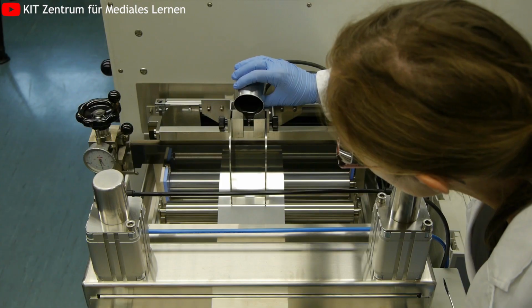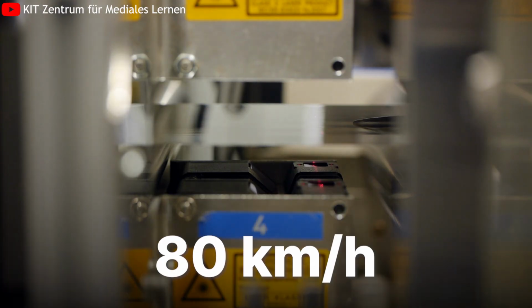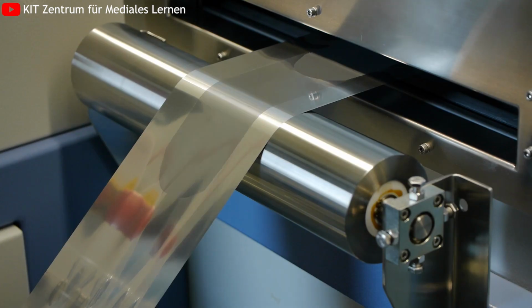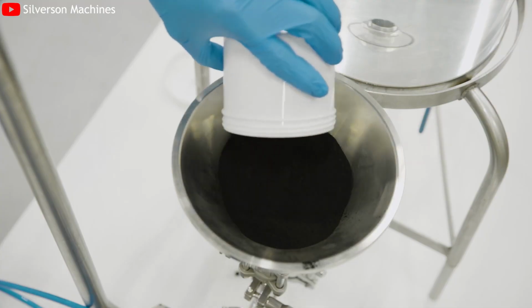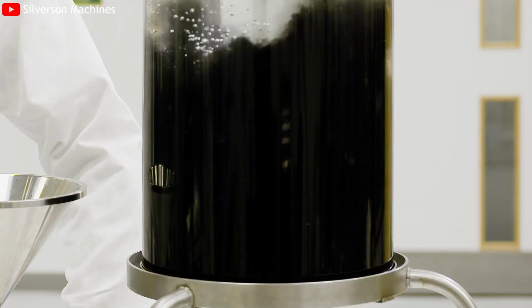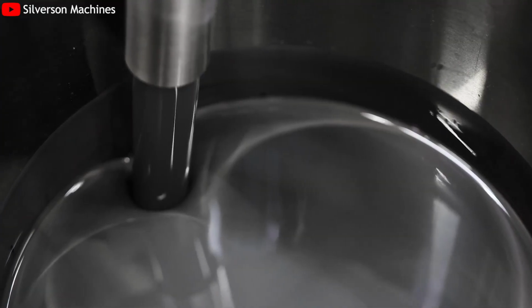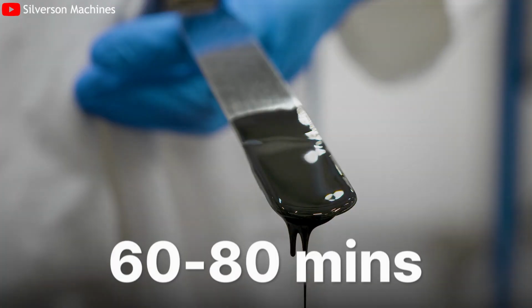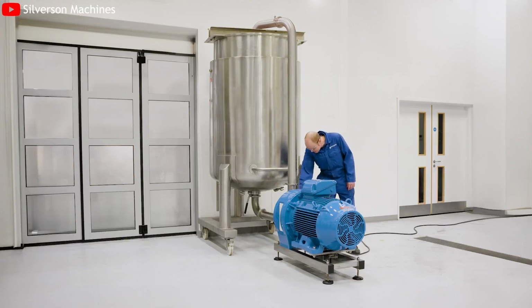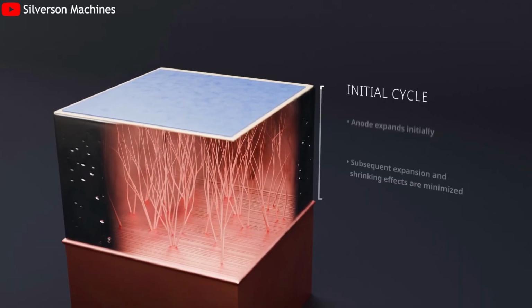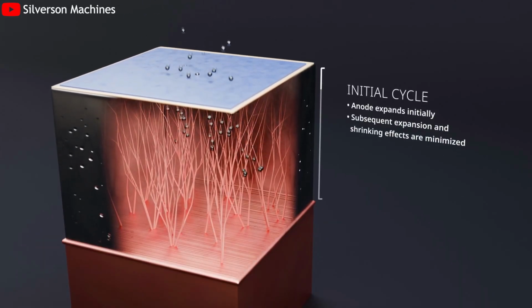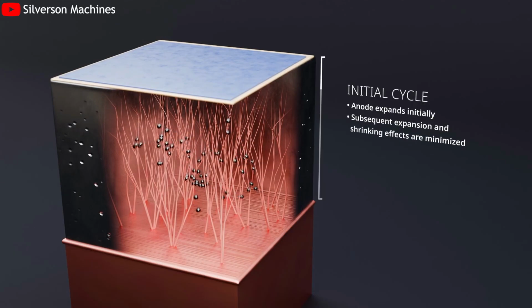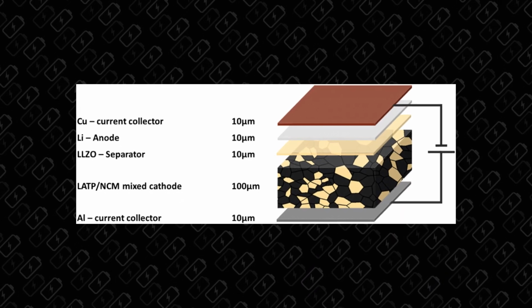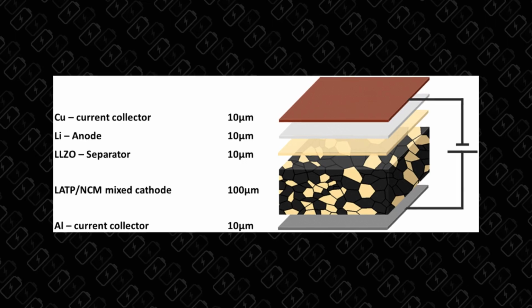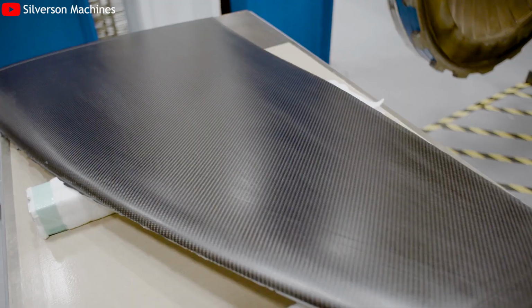Imagine trying to wrap a sheet of glass thinner than a human hair around a spool at 80 kilometers per hour. Welcome to the solid-state production line. This is where the economics die. The lithium-ion industry is built on the roll-to-roll process. Giant machines coat, dry, and wind electrode sheets at speeds of 60 to 80 meters per minute. It is a high-speed, high-tension process. To beat current batteries in energy density, the solid electrolyte layer must be aggressively thin, under 30 micrometers. If it is thicker, the heavy ceramic weight cancels out any energy gains. At 30 micrometers, ceramic oxides like LLZO are as fragile as a soap bubble made of glass. You cannot run them through a high-speed winder.